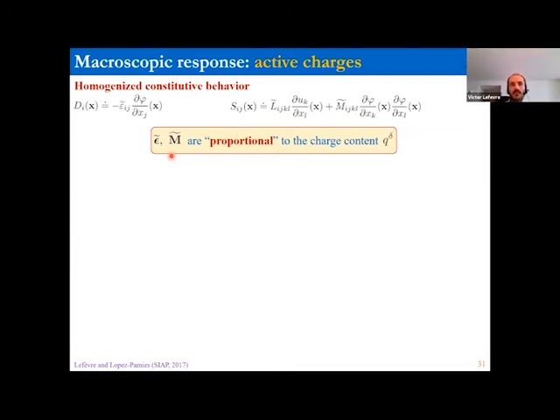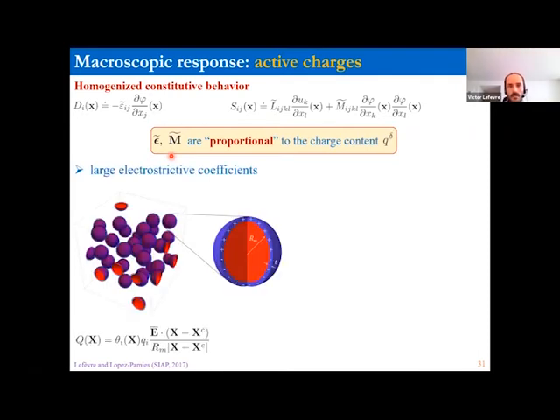These quantities are directly related and, quote-unquote, proportional to the charge content in the composite. And so that's really nice, because now we looked at some results, again, for an isotropic distribution of spherical particles in red, now with this interface region where we have space charges located. That's the model for the distribution of the space charges. Say a few words about this in a second.